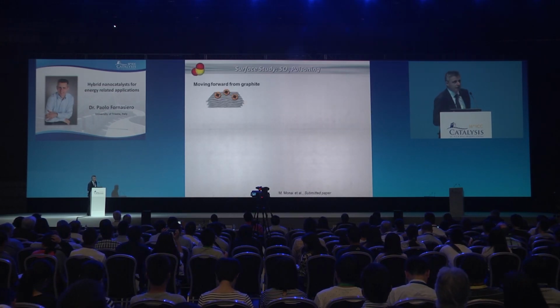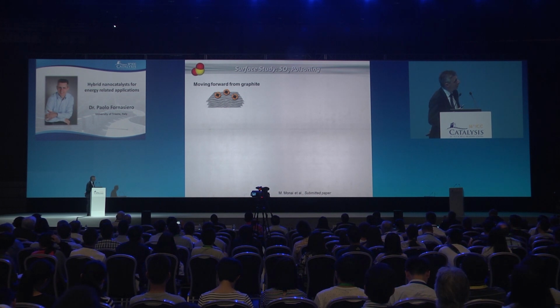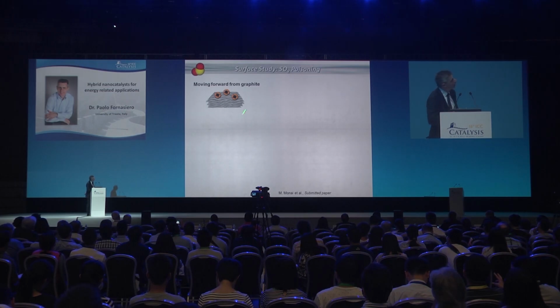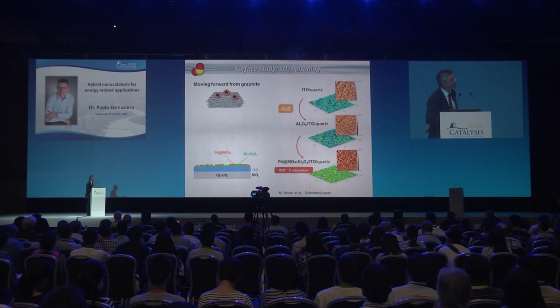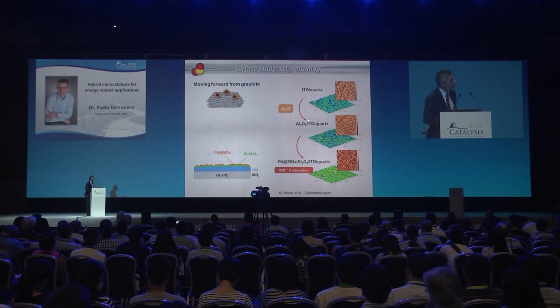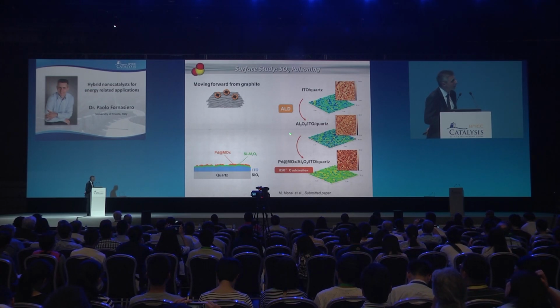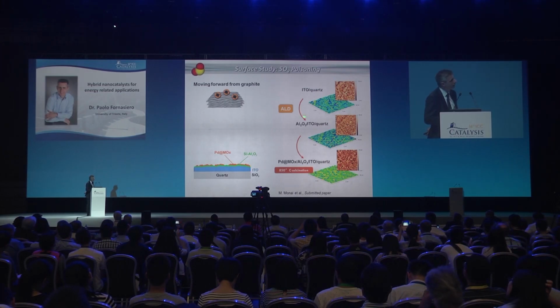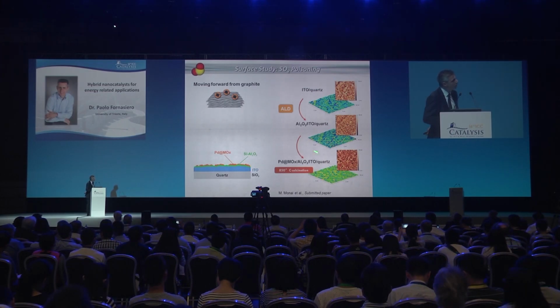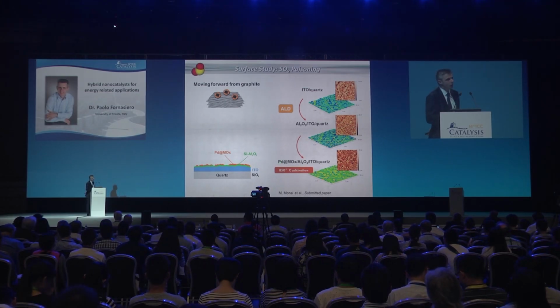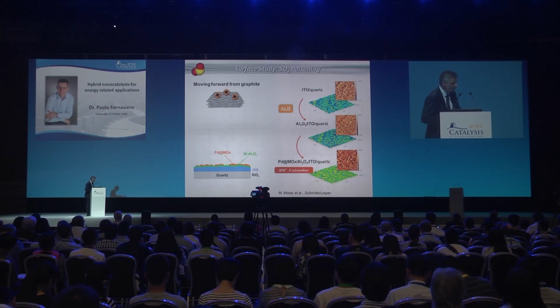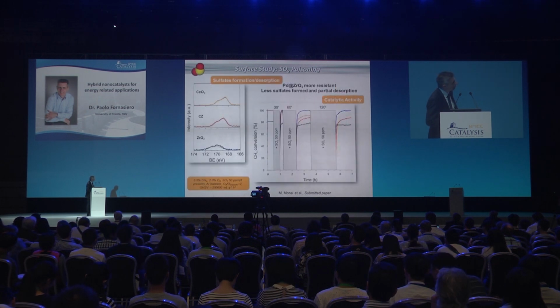Then we look at the effect of SO2, which is also a very serious problem for this type of catalyst, and we move from this original simple model catalyst to something more sophisticated, closer to real catalysis. We start from indium tin oxide, cover it by atomic layer deposition with films of alumina, and then impregnate, this time, with core-shell units of palladium at zirconia, ceria, and ceria-zirconia. After calcination we obtain something rather similar to the real catalyst.